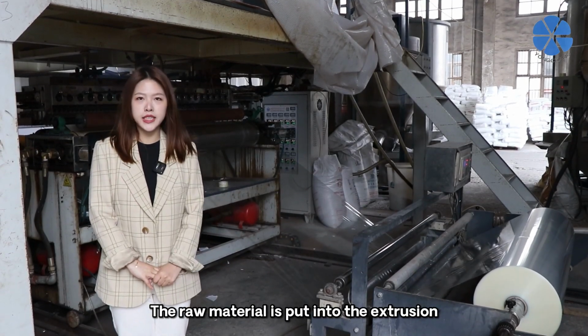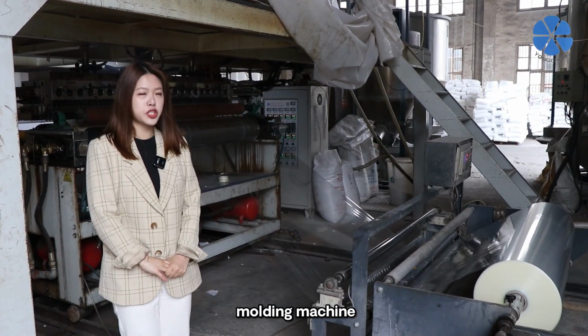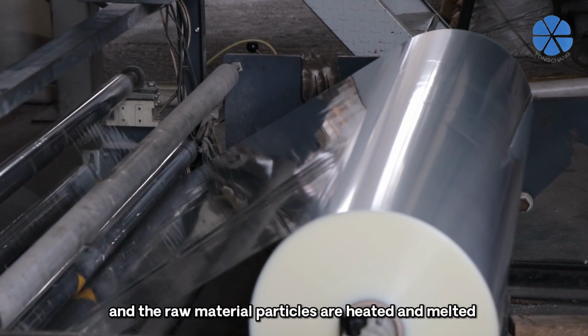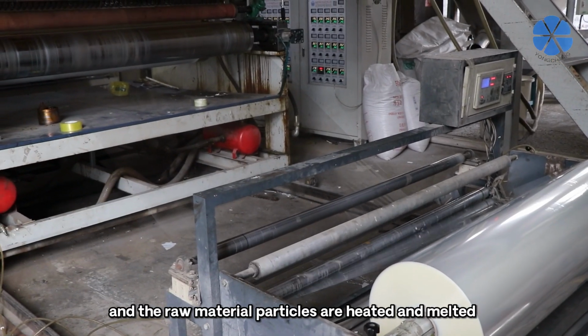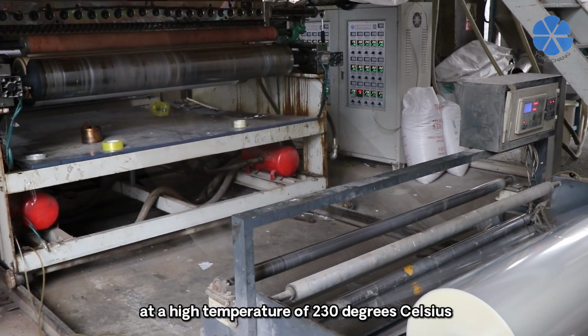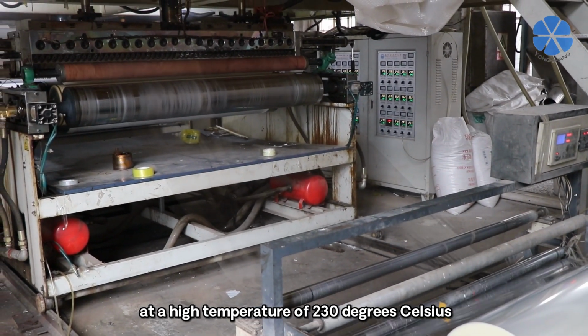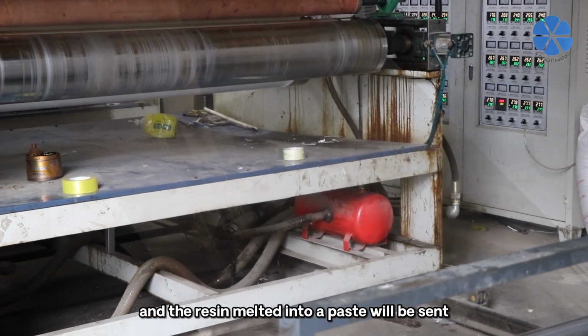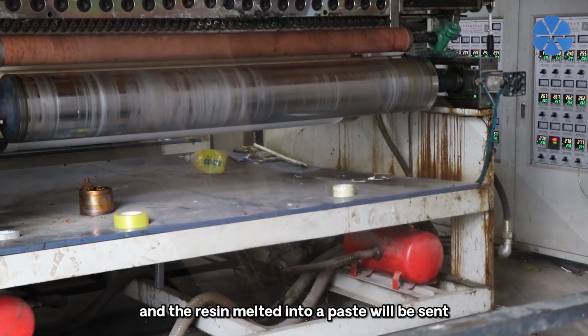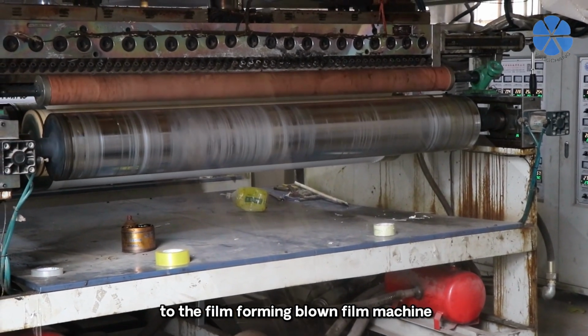The raw material is put into the extrusion molding machine. And the raw material particles are heated and melted at a high temperature of 230 degrees Celsius, and the resin melted into a paste will be sent to the film forming blown film machine.